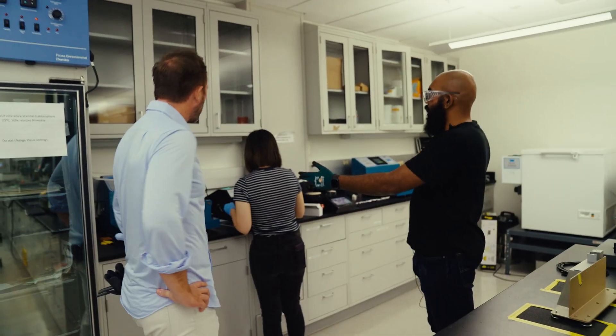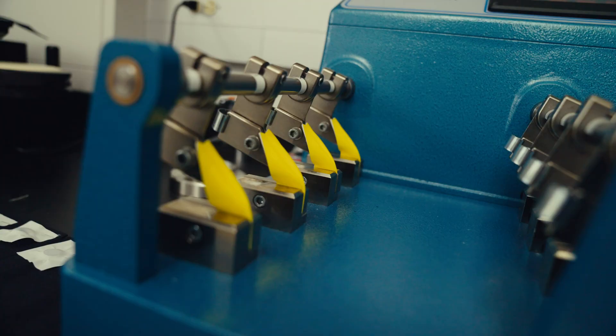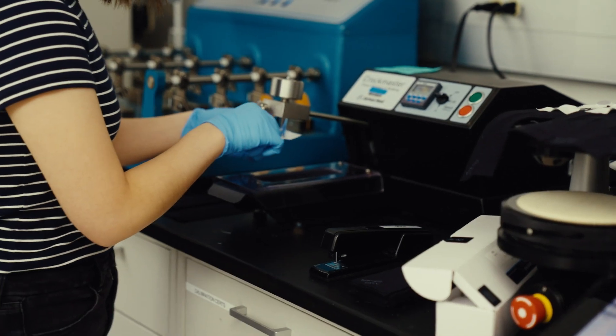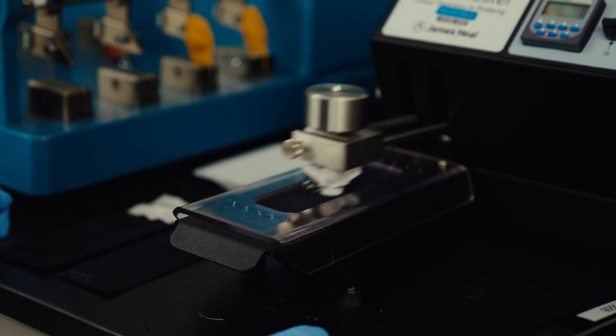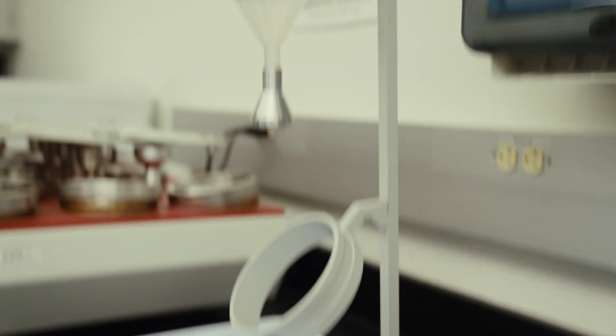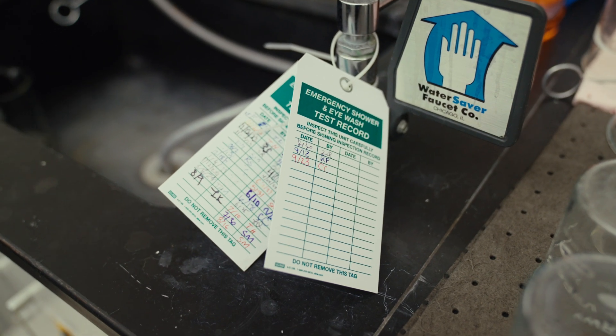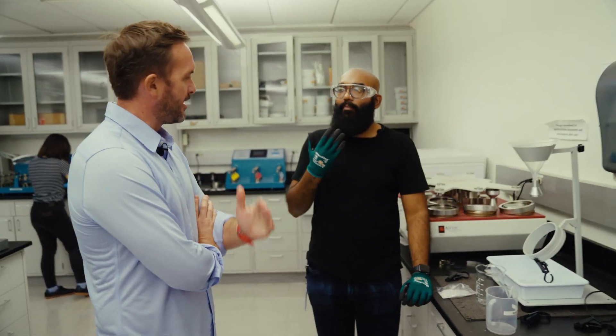These two are what we call Ballyflex machines. You want your material to not crack even under repeated bending, so that's why this test is really important. What my coworker Michelle is doing is what we call a crocking test — she puts that lever down and it rubs repeatedly to see how much color is coming out of a material. Over here, water poured in with a nozzle that has specific holes to simulate rainfall. On the other hand, this is where you put your material in — water is being pumped from underneath and at some point under pressure, water would come out.